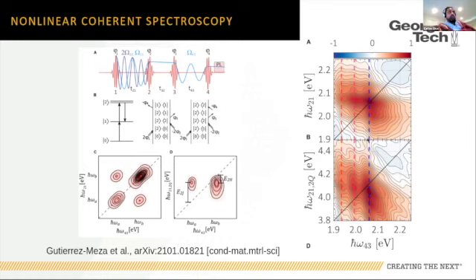We go to the 2 quantum coherence. This axis now, you notice that the energy is twice the energy of this. This is a 2 quantum coherence that we select out by our phase modulation scheme. And we correlate that with the same 1 quantum coherence from our other pair of pulses. And we find that the 0, 0 peak is lower in energy than the 2 quantum diagonal, okay? But these lower energy peaks that we ascribe to the 0, 0 of the J aggregate are higher in energy.